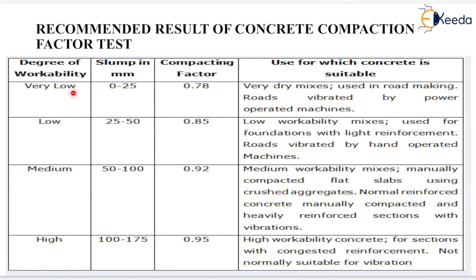Now for very low workable concrete, the slump will be 0 to 25 mm and the compacting factor will be equal to 0.78. Now it is used for very dry mixes, used in road making, road vibrated by power operated machines. Similarly, for low workable concrete, for medium workable concrete and for high workable concrete, slump is written here, compacting factor is written here and the use is written here like this.